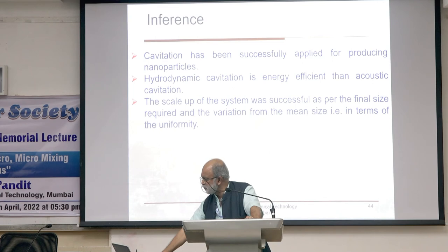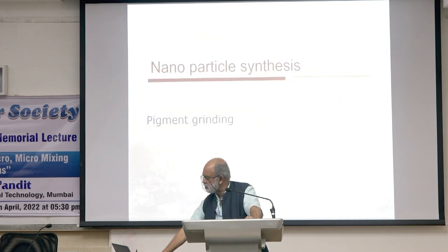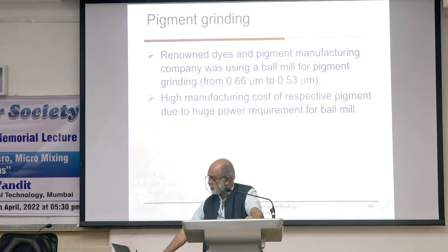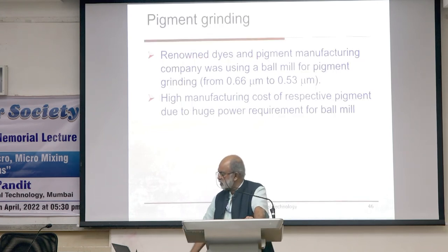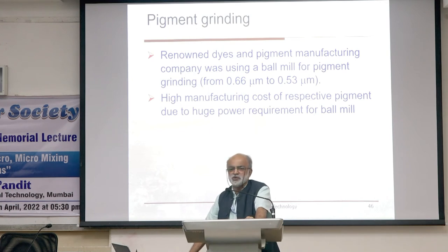Hydrodynamic cavitation is more energy efficient than acoustic cavitation. This is true only for specific applications. So, pigment grinding. A renowned dyes and pigment manufacturing company was using a ball mill for pigment grinding to reduce the particle size from 0.66 microns to 0.53 microns. And you all know that initial reduction in the size is much easier, but to reduce it from fine size to finer size uses a significantly higher amount of energy. So this resulted in a high manufacturing cost of the respective pigment due to huge power consumption using the ball mill.